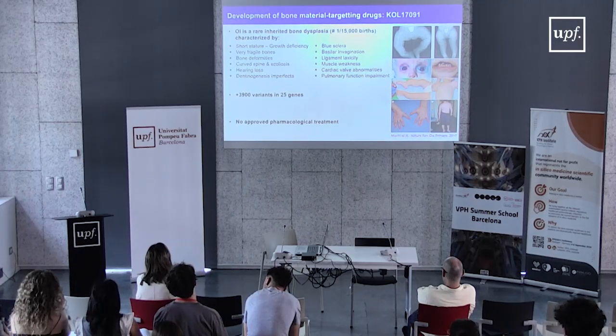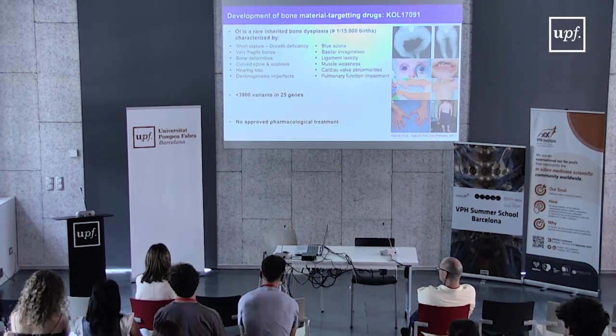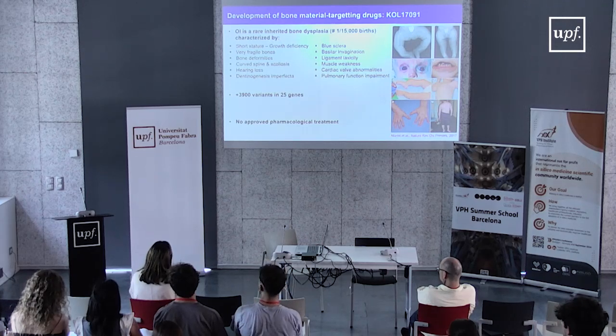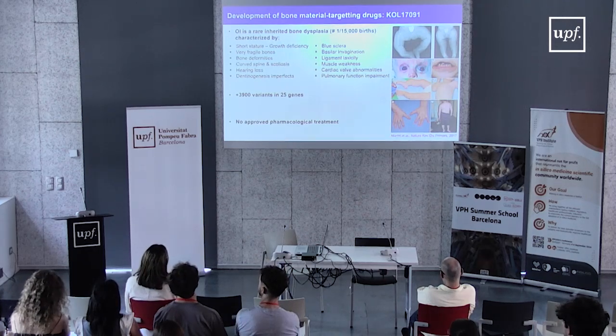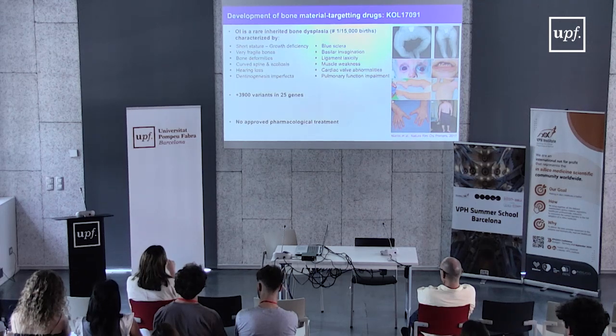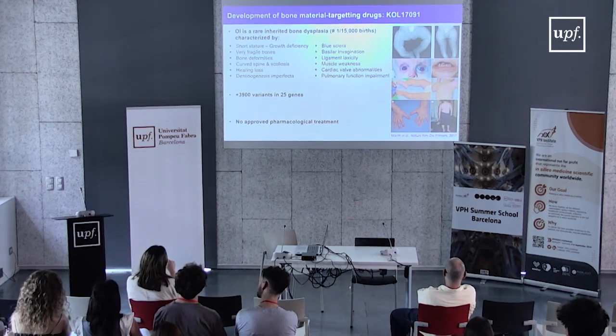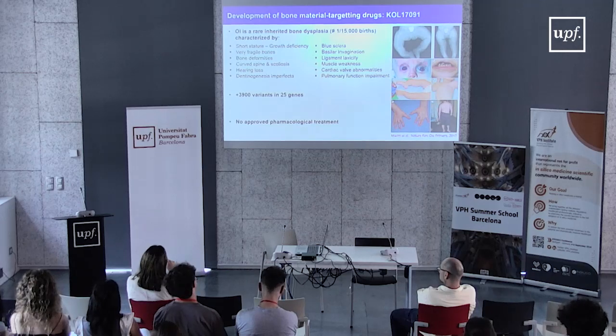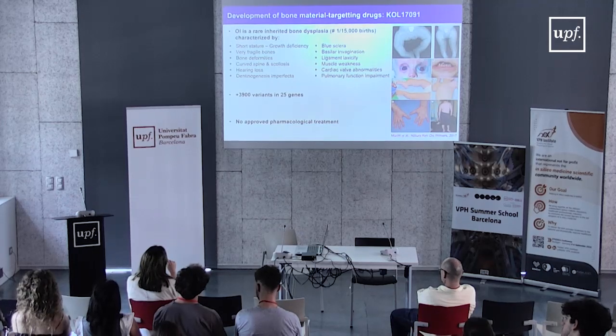And because the collagen is abnormally deposited in the bone matrix, you also have problems of hearing. There is hearing loss. And type 1 collagen is the most abundant protein found in bone, but not only in bone. And this explains why you have dentinogenesis imperfecta, which is a problem of the dentin inside the tooth. Blue sclera, because the cornea and the sclera of your eyes contain type 1 collagen, and you can have muscle weakness, cardiac valve abnormalities, and pulmonary impairment.